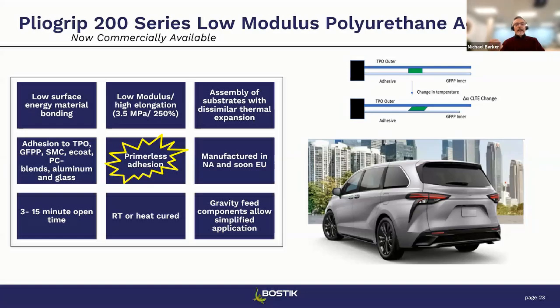It's got a low modulus and a high elongation, which will then account for the dissimilar CLTEs of the substrate. It's got excellent adhesion to not only the TPO and the glass-filled polypro, but also to SMC, E-coat, polycarbonate, aluminum, and glass. So it's quite a robust adhesive. It is now commercial. We have a customer on the West Coast that is using this to build assemblies. It's got an open time or a working time of 3 to 15 minutes, and that can be varied. And this adhesive can be cured at room temperature or heat cured.